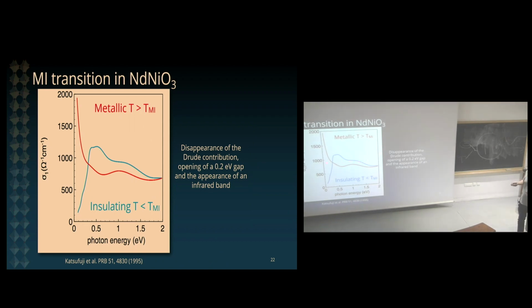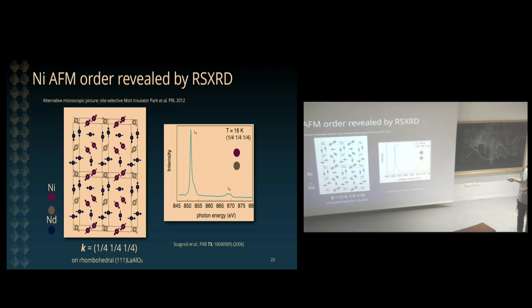Neodymium nickelate across its metal to insulator transition has a big change in its optical properties, as you can imagine. So in the metallic state, we have a well-defined Drude response, while in the insulating phase, this Drude peak disappears, and the spectral weight is transferred to an infrared band, which is very large. Right. So we use this trick to probe the electronic properties out of equilibrium using optics.